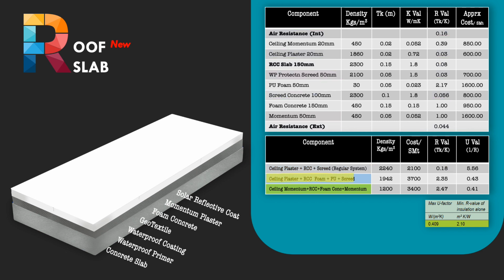System 2, we have considered cement plaster for interior ceiling, waterproof coating over slab, protection screed 50 mm, followed by 50 mm layer of PU foam insulation. Over the PU insulation, slopes will be provided with screed concrete. The system provides excellent thermal insulation. Only issue would be that the screed concrete does not bond to PU foam, hence acts like a floating slab and tends to develop cracks over time. R value of system is 2.35 and U value 0.43, which is very close to recommended standard.